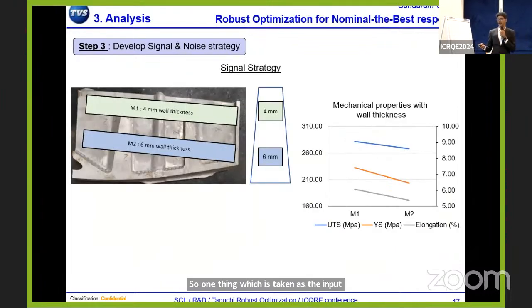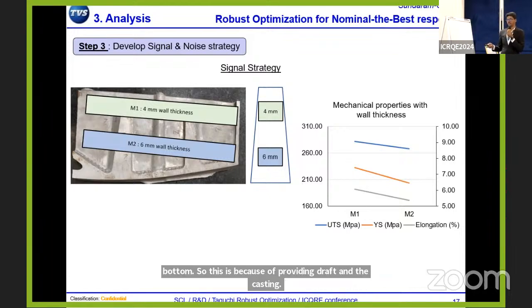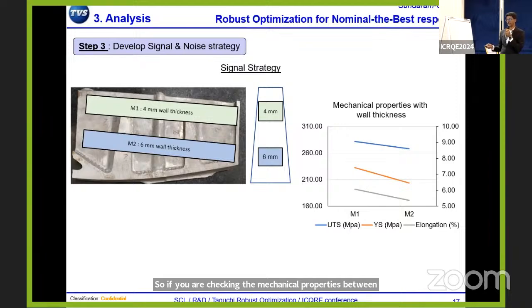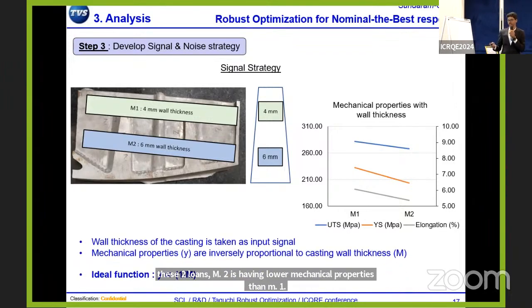In the selected cut sample, there are two regions of wall thickness. One is 4 mm wall thickness at the top and 6 mm wall thickness at the bottom. This is because of the draft provided in the casting. If you check the mechanical properties between these two zones, M2 has lower mechanical properties than M1. So Y is inversely proportional to M.